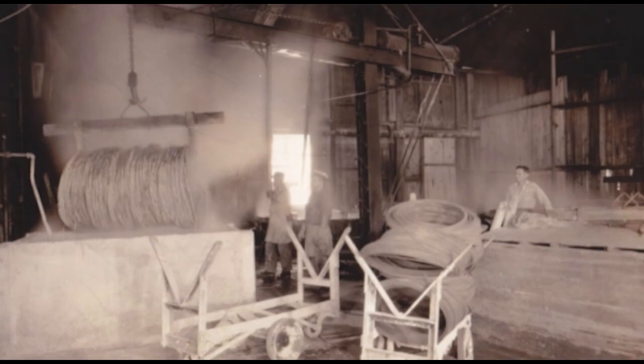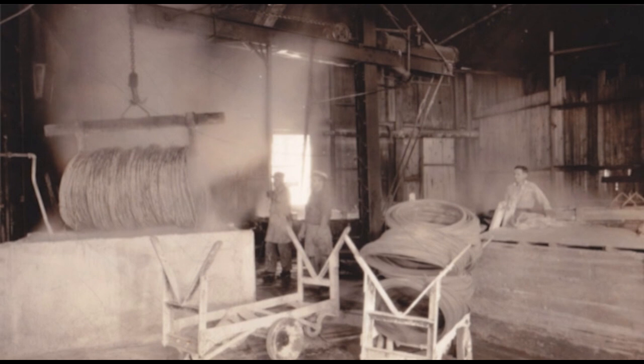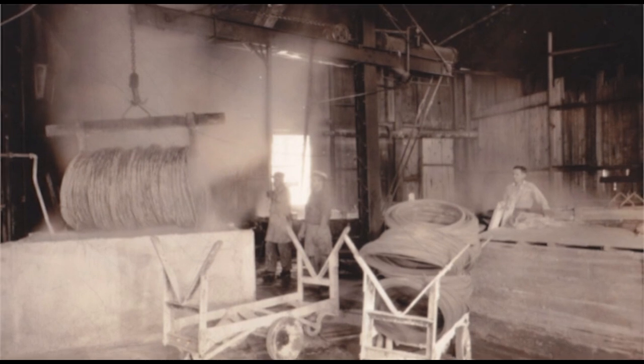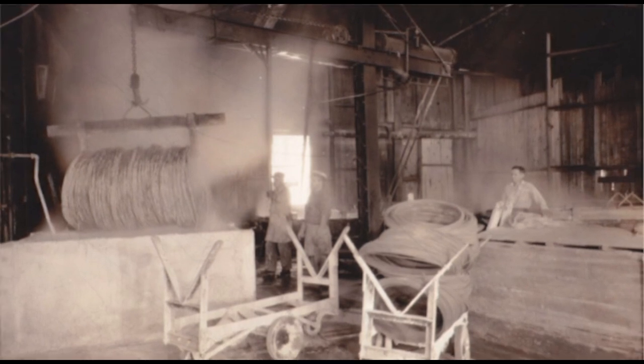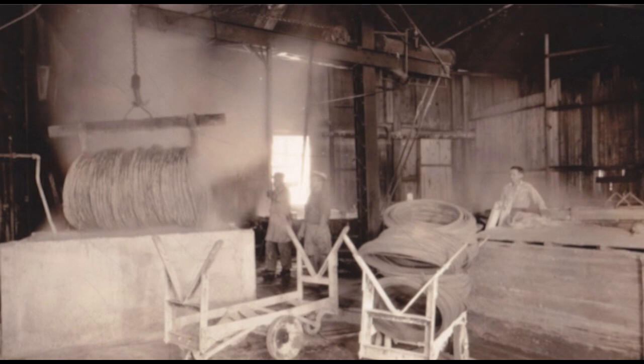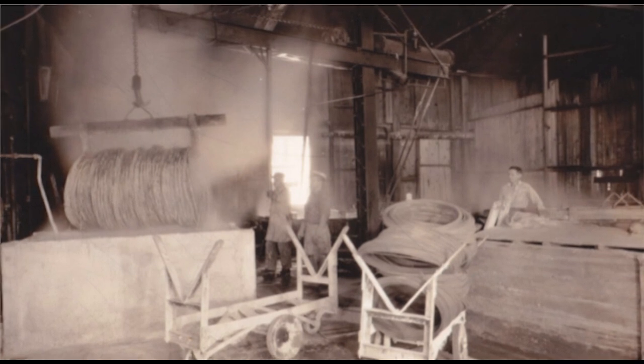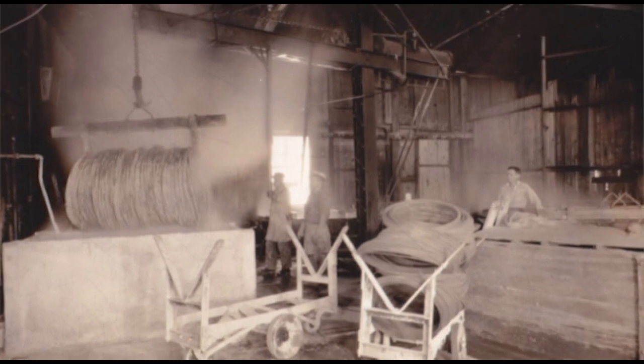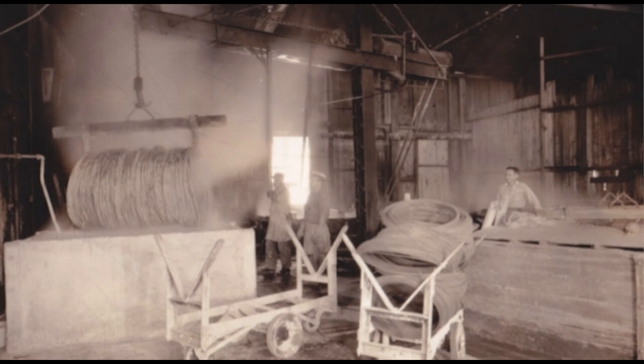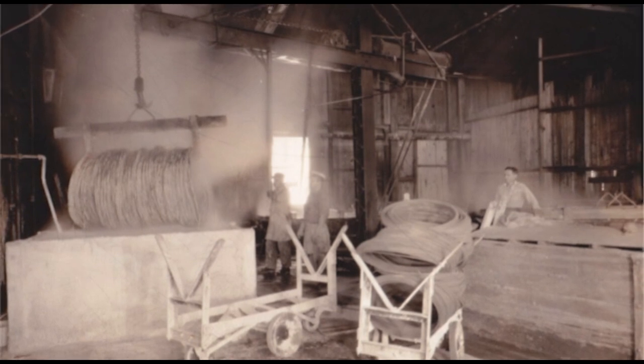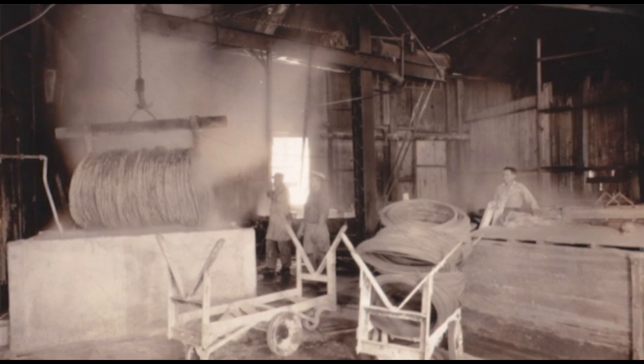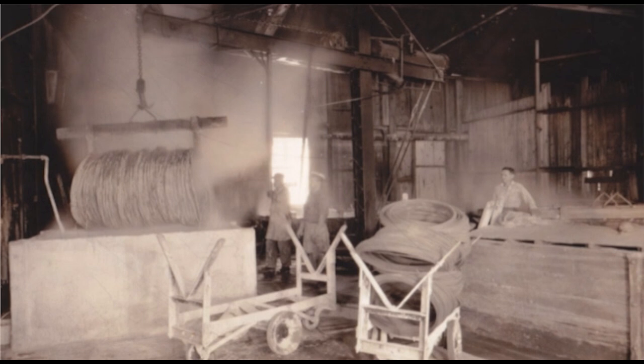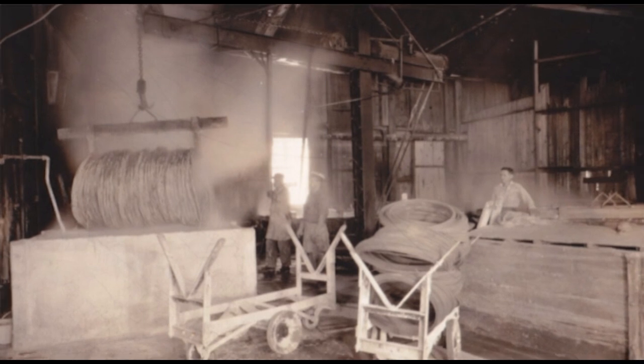The vats were made of Stony Creek granite and were used for many years. After about 15 minutes in the vat, they were lifted out to a spray rack. Once the mill scale was sprayed off, the coil is bare metal. The wire mill had a laboratory with a chemist and laboratory technicians who checked the chemical composition of the sulfuric acid and other chemicals used throughout the plant. The acid could be reused, but only as long as the composition was correct.